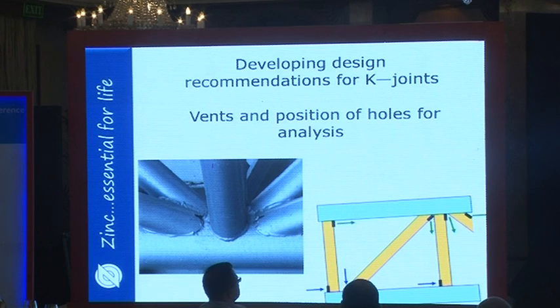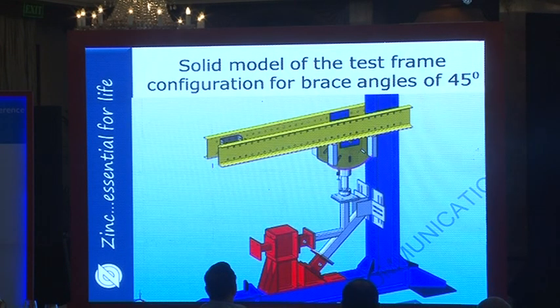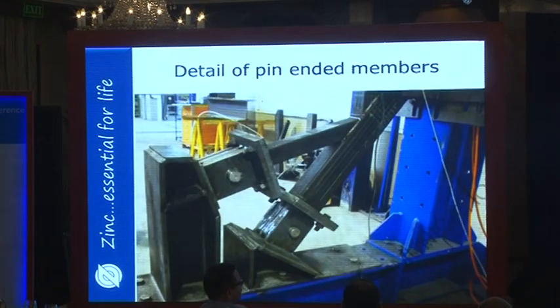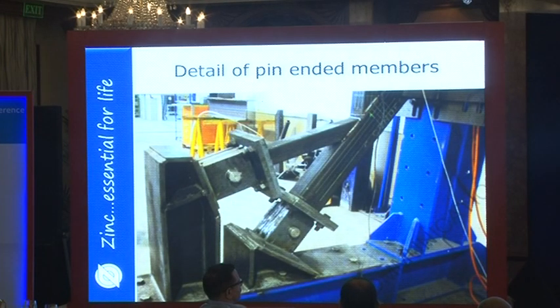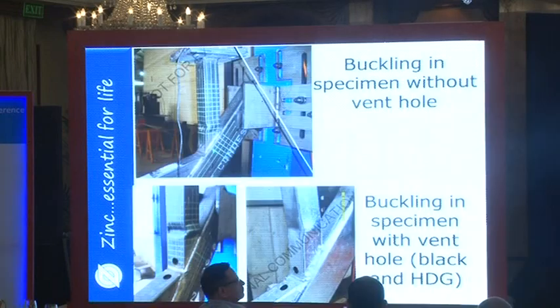So we've studied this. We did a project at the University of Cantabria in Spain. They made an apparatus that looked like this. We were able to pressurize it with the cylinder that's shown in the vertical axis there, and to determine what the point of failure was when we stressed these beams. We also did, this is just the actual picture of it, showing the loading of these, and this has the venting holes in the right places.